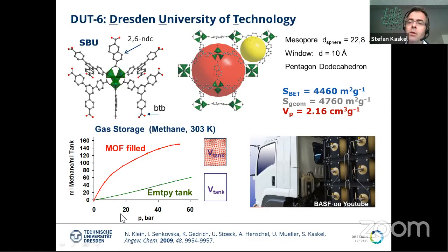And at that time, these materials were very good in gas storage. For example, here you see a typical delivery curve from gas storage experiments. If you put such a MOF in a cylinder, the storage capacity is greatly enhanced by a factor of 2 to 3, even at room temperature, because the methane gas or the natural gas basically assumes a higher density state in the pore as compared to the pure gas in an empty tank. And this allows to enhance the storage capacity of these type of containers. And this is fully reversible, this type of behavior, and was an important industrial target at that time, and also followed by BASF.